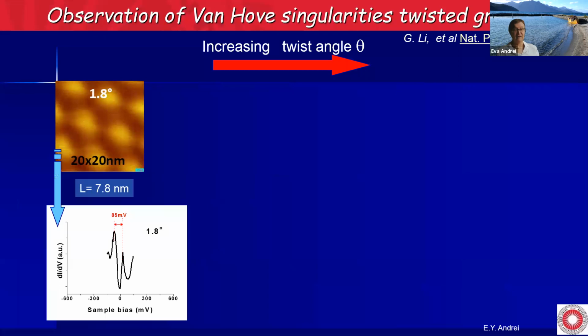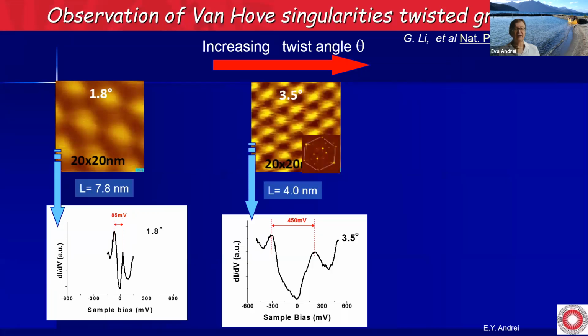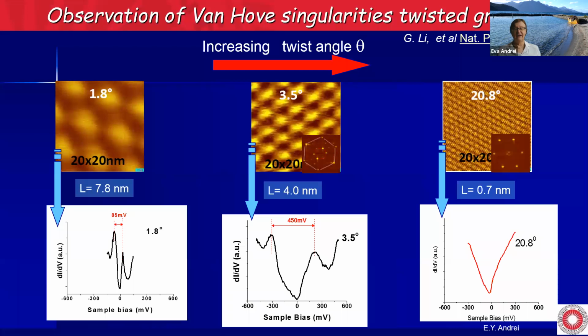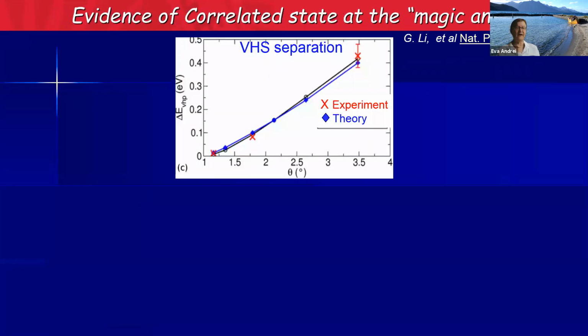Then we could look at various angles. So this is again the same data for 1.79 degrees. Then you go to a larger angle, 3.5 degrees. The peaks are further away from each other. And at 20 degrees, they're outside of the field of view of our scan. So if you plot the separation of these Van Hove singularity peaks as a function of twist angle, you get a monotonic dependence, which pretty much agrees with theory.